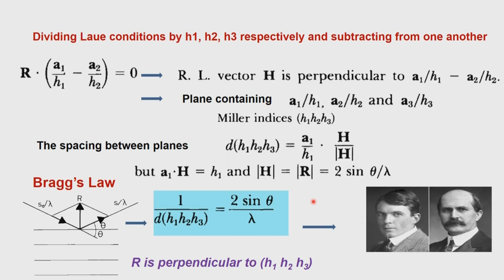So, the geometry of the unit cell and its a, b, c, alpha, beta, gamma values and its corresponding spacing of the planes inside the crystal, both we will be able to get using this equation. So, the entire geometry of scattering can be obtained. The other two equations which we discussed earlier on, scattering factor and the electron density, represent essentially the presence of the electron density inside this crystal. So, a combination of this to give us the geometry and a combination of the Fourier transform equation to give the electron density, in principle, therefore, should help in solving the structure.